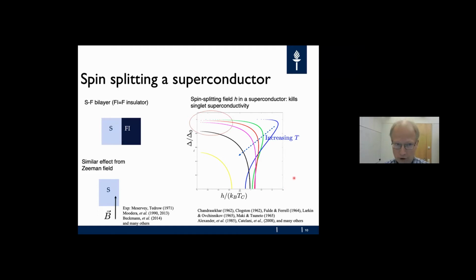At low temperatures, the phase transition is actually first order, so there is a regime of exchange fields where there are basically three solutions, one of them unstable, to the self-consistency equation for superconductivity. At high temperatures, it becomes a second order phase transition, so there is only a single valued delta.